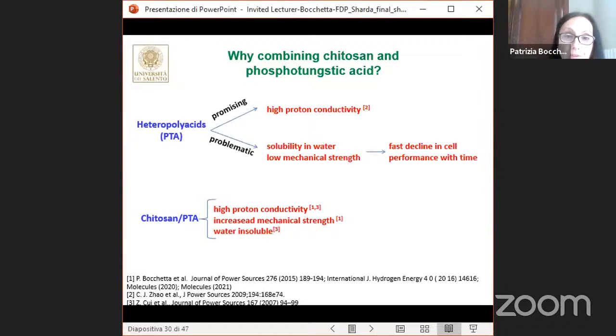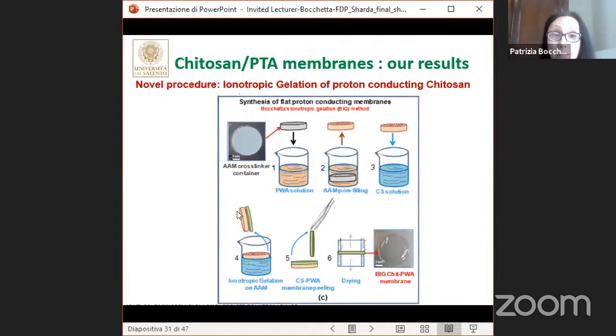Among the different approaches, we have noted the capability of phosphotungstic acid to form an insoluble complex with chitosan through strong electrostatic interaction. This insoluble property was proposed by Cui et al. about 15 years ago. In that paper, the membranes were formed by a two-step solution cast technique and a second step of functionalization. However, few papers have developed this promising strategy with novel approaches. So we have proved for the first time the possible application of ionotropic gelation of chitosan to the synthesis of chitosan membranes with phosphotungstic acid.